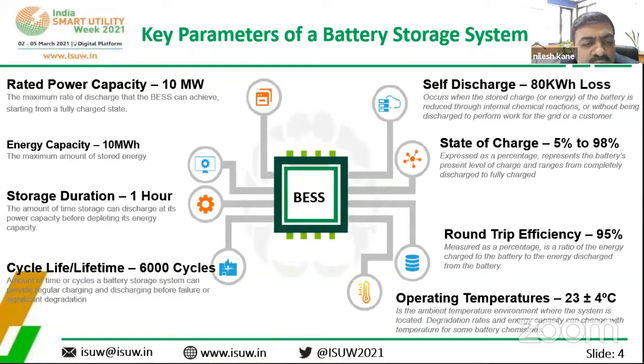And these are the limits: rated capacity is 10 megawatt hours, 10 megawatt, 1 hour, and 6,000 cycles is the lifetime of the battery. We are operating at 23 plus or minus 4 degrees centigrade. We have kept 200 tonnage of air conditioning for maintaining this, with round trip efficiency of 95%. State of charge from 5% to 98%, obviously almost 0 to 100% for this lithium ion battery storage. And the self-discharge loss is 80 kilowatt hours. Next.